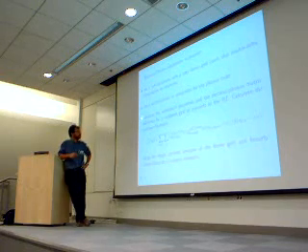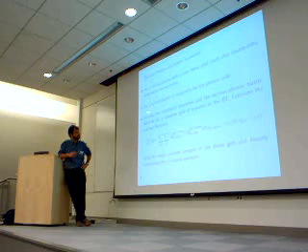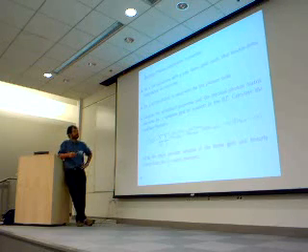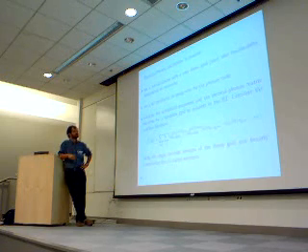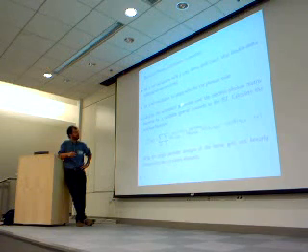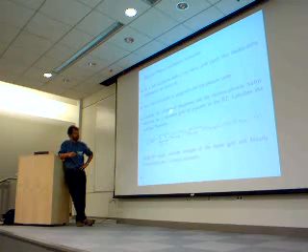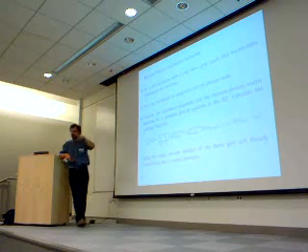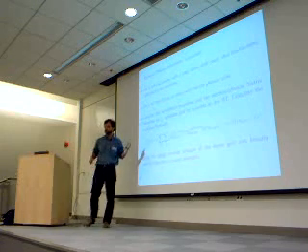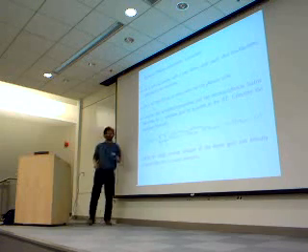So one does again a self-consistent calculation with a dense but not extremely dense set of K points, and on the basis of this calculation one does the full calculation for the vibrational properties, which are sampled on a regular grid of Q points, the way you have seen two days ago.